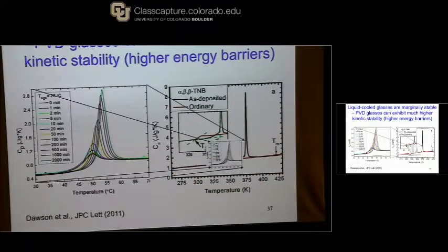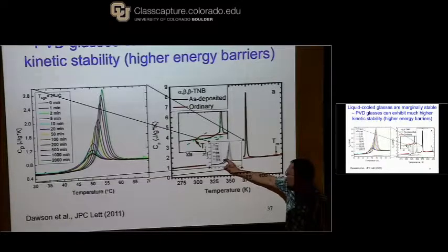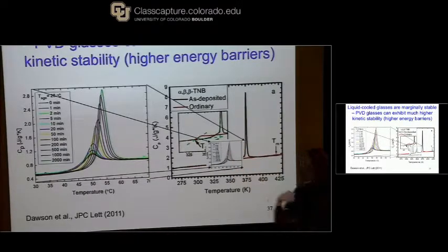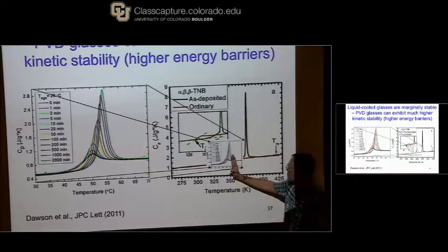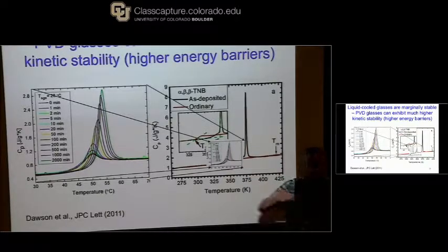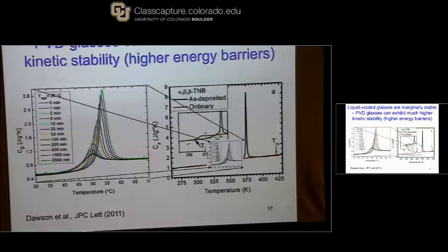Now, if I just take that and I adjust the scales and put it on top of the vapor deposit experiment, you see, well, this is the first 2 decades of aging. It's slowing down logarithmically. So there are a lot of decades, a lot of curves in between that one and that one. We've tried to estimate how many decades of aging in many different ways, and maybe it's 10 to the 8th. It's hard to do a good extrapolation there. What's true is that these vapor deposited glasses show extremely high kinetic stability, much higher than liquid-cooled glasses.